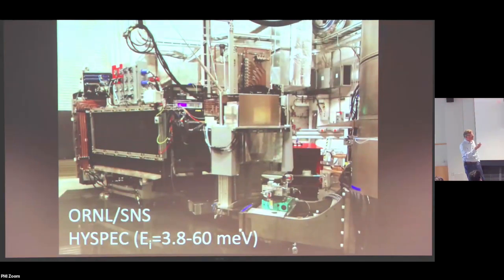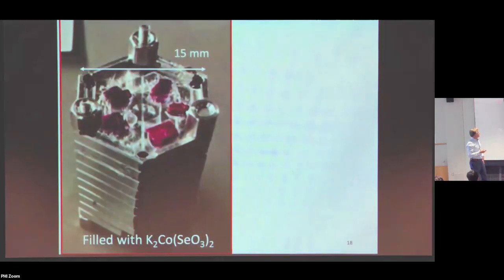But for the cobalt compound that we're going to start talking about, we used instrumentation at the Oak Ridge National Lab. And this is a hugely complicated thing. We won't go into details about it. But fundamentally, you can be assured that what's happening is essentially the scattering triangle. Here's the incident vector, here's the scattered vector, and I'm keeping track of energy and momentum transfer. And you're going to see the scattering cross-section in absolute units as a function of wave vector and energy transfer. And this is what the sample tends to look like. We tend to have to mount many samples together to get enough intensity. I told you we're always at the limit.